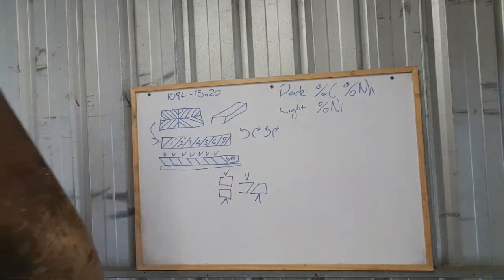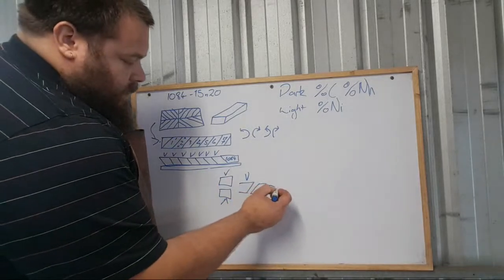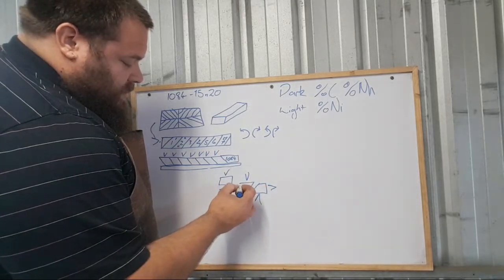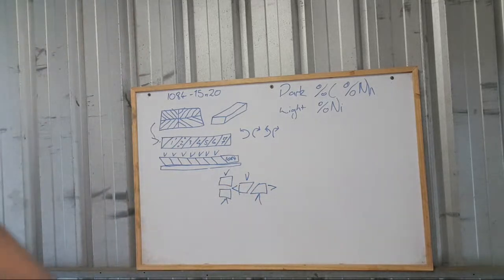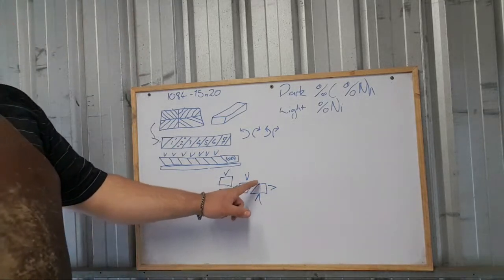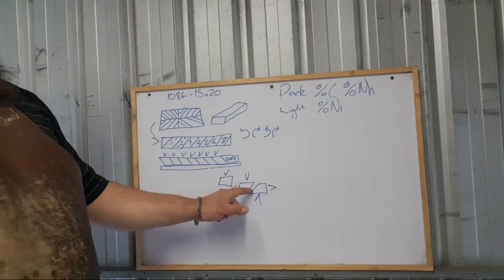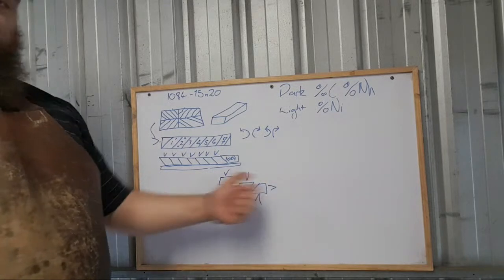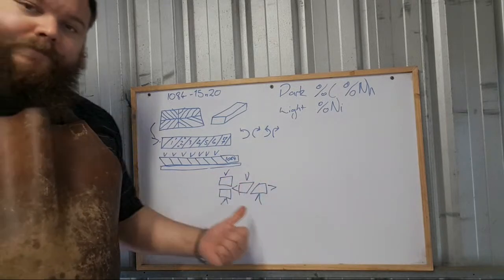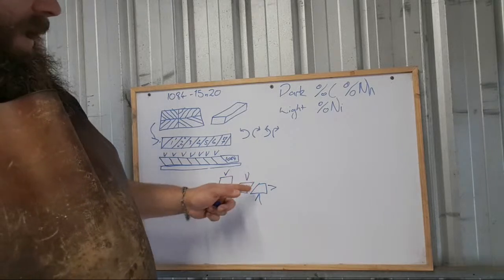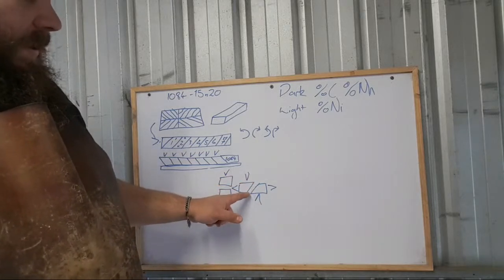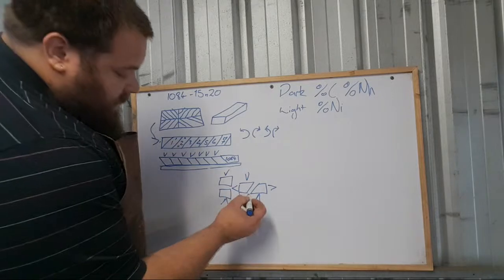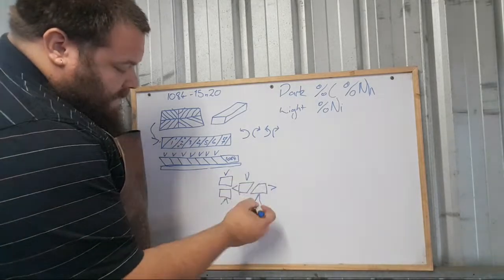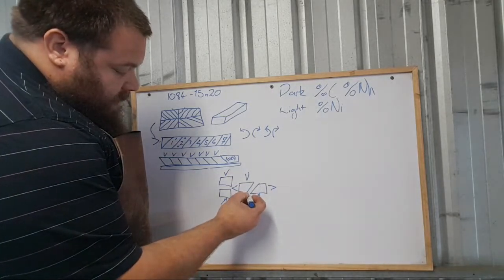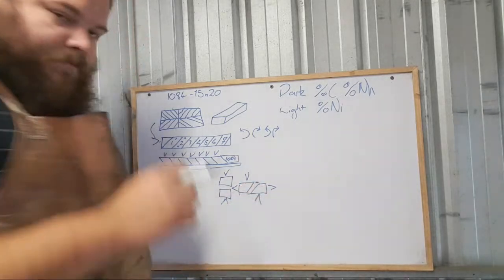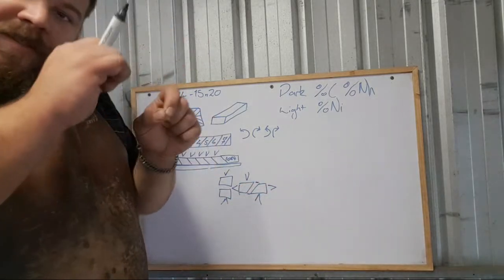And so what wants to happen is that this one wants to shoot that way, and that one wants to shoot this way. Right, so without having the seams completely welded, A, your shear stress is just going to push them apart, and B, any flux that is in here is going to seep into these areas, because what will happen is that as the compression hits, these toes will push apart a little bit and leave you with a seam of borax.